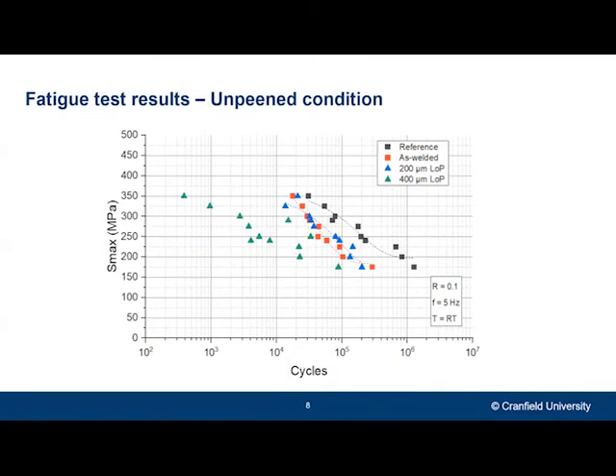Things start to get a bit more interesting when we consider these lack of penetration defects. So as you can see in blue triangles, when the welds have a defect that is only 200 micrometer deep, there's no difference in fatigue life when we compare it to the as welded samples with no defects, which you can see in red. And this is, of course, within the typical scatter that you would see in fatigue tests. On the other hand, if the defect is 400 micrometer deep, which you can see in green, there is a reduction of about 80% in fatigue life, which is quite substantial.